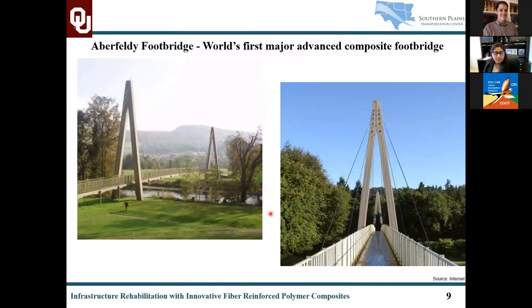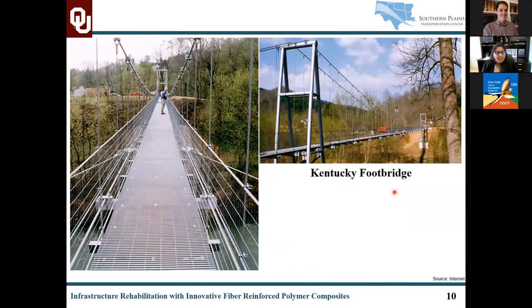developed using pultruded GFRP e-glass fiber and polyester resin combinations. The cables were Kevlar 49 fibers with low density polyethylene. So combinations of different kinds of fibers and thermosetting resins, a deck with pultruded GFRP sections, and so on and so forth. If we look at the Kentucky footbridge, this is a composite deck with galvanized steel towers and suspension cables that support this pultruded fiberglass. The original wooden footbridge that was built in the 1930s had fallen into disrepair, and 100 years of maintenance-free service is expected with this rehabilitation performed with FRP.